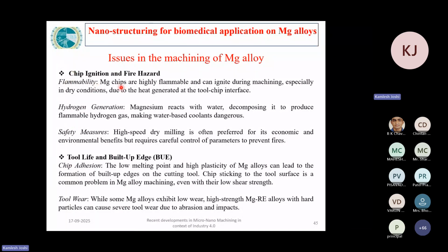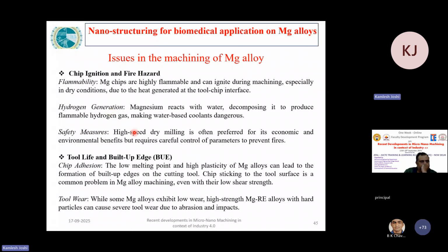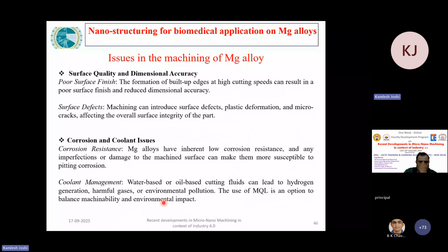So flammability: magnesium chips are highly flammable and can ignite during machining, especially in dry conditions. Hydrogen generation happens. Safety measures are some of the issues in high speed machining. Tool life and built up edge formation happens because magnesium is a highly ductile material, and the chips which are formed adhere on the tool material, which further deteriorates the surface of the machine, and tool wear is also one of the issues.